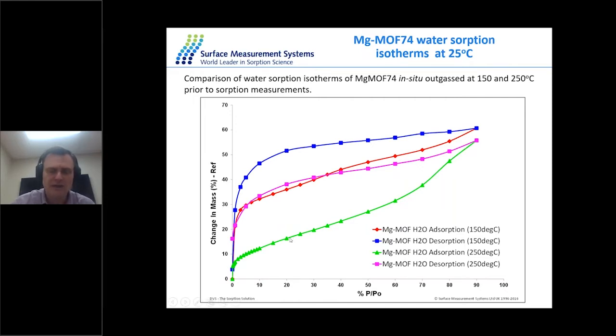So if I outgas material MOF 74 at 250 degrees, my isotherm is showing adsorption in green, desorption in pink. What you can see here, we have huge hysteresis at quite low capacity. Now the same material, outgassed at 150 degrees, shows adsorption in red, desorption in blue, with small hysteresis. First thing you can see is the differences in the hysteresis gap.